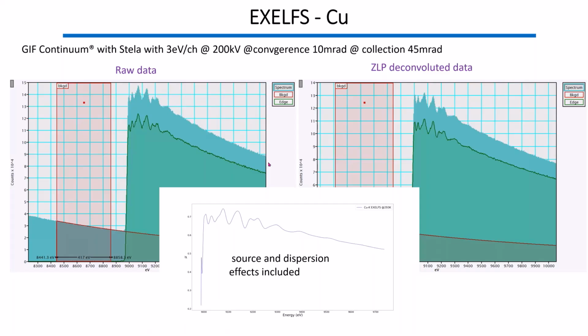And the wiggles in the fine structure, the extended edge, are pretty broad, right? So you probably won't gain a whole lot from going to a higher dispersion. And you also have lifetime broadening as well. Yeah. We're not yet reaching superior signal to noise so far at the moment. Especially, we have to use 1 to 3 nanoamps to boost the signal to noise, so we also have to be mindful of the sample dimension. So in the end, this is so far our compromise or trade-off.